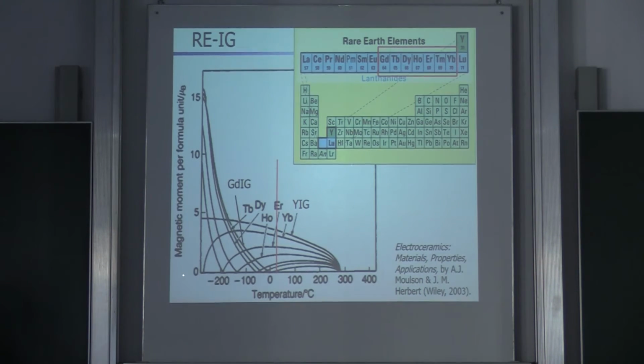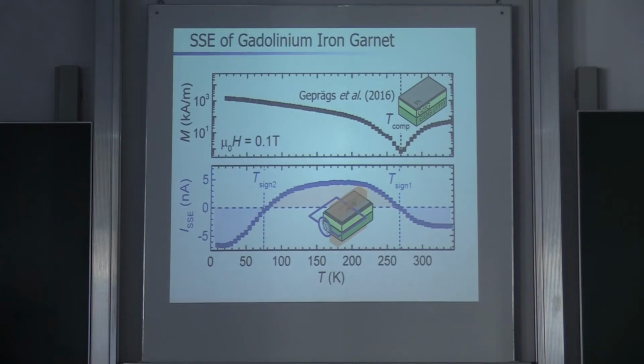So here you see, for example, and these are very old experiments actually, the magnetization of these rare earth substituted iron garnets. And this one here would be the YIG, right? This is just a very boring type of mean field magnetization. But the interesting thing is that if you replace this by other ones, you get curves at which the magnetization vanishes at some point. In this case, there is a cancellation between the magnetization due to the rare earth ions and the magnetization due to the iron. And these are called compensation points. I will not go into the details.